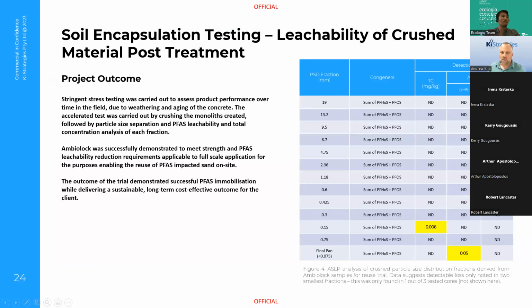Next slide, please. And then to test the durability of the stabilizing solution, we destroyed those monoliths, ground them down, separated them into various particle size fractions, and then had a look at how much PFAS would leach from each fraction. And as you'll note from the graph, for most of the fractions, PFAS was not even detectable after degradation and destruction of the cores following treatment.